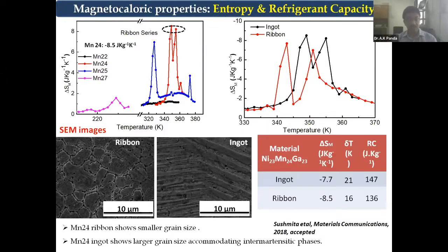So this is what we show you. The ribbons have much smaller grain size. You can understand from the optical micrographs of the nickel manganese gallium ribbons against the ingots. When you plot the delta entropy with respect to temperature and compare the ingot and ribbon, we find that the entropy of the ribbon is like 8.5 and the ingot is 7.7, but the ingot has a fairly high relative cooling capacity, 147.